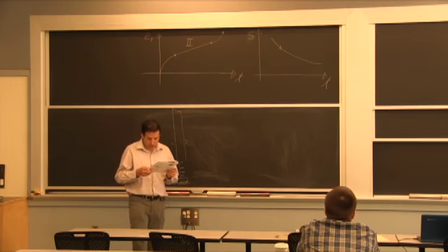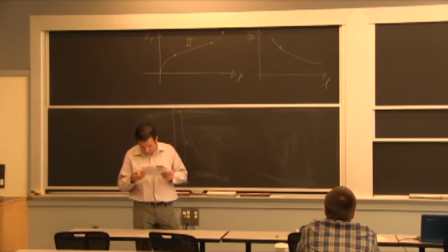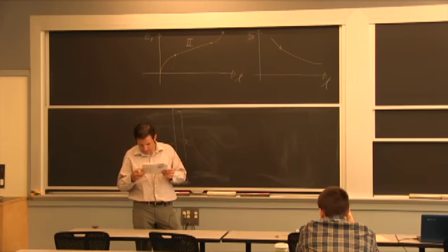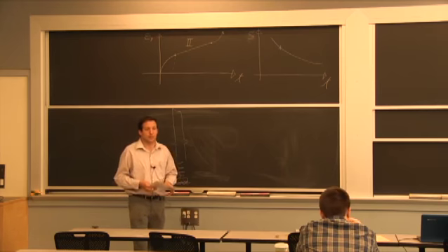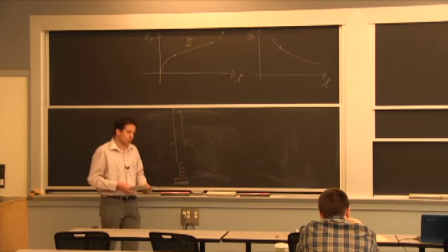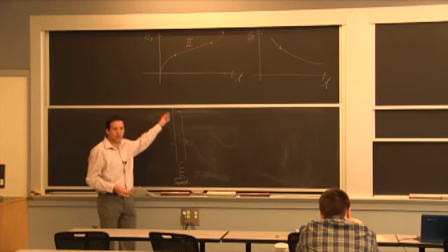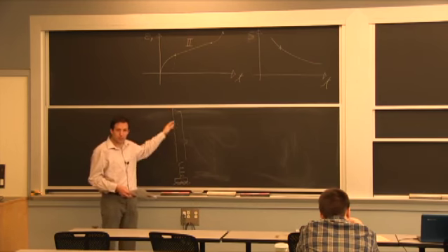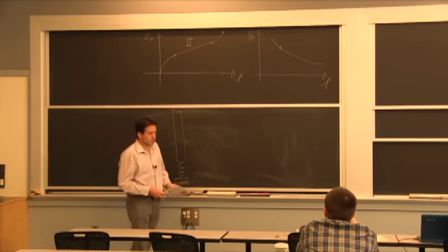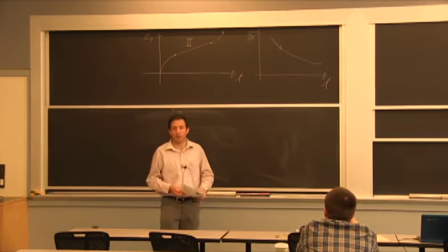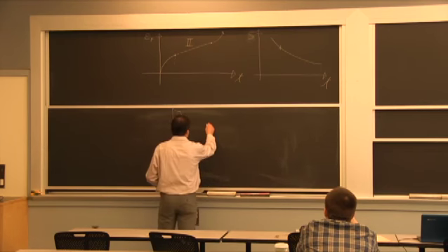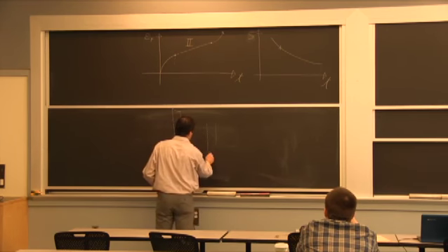I gave you a chart collected a while ago about the different alloys. Essentially it says the single crystal is a technology of the 80s, more or less. Before that, they were doing directional. So directional is a little bit the same idea, where you try to get a gradient in temperature, but you don't just grow a single grain. You grow multiple grains that will have an elongated shape like this.